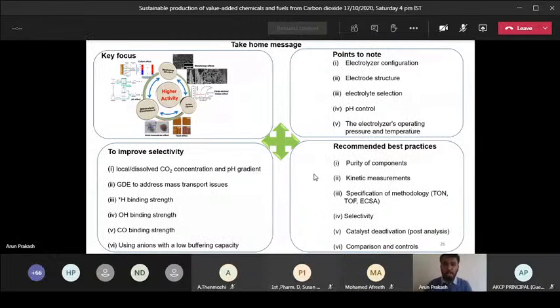And higher activity. When you want to get a higher activity, you have to focus on the electrolysis environment as the main thing, and the nanomaterial size, shape, grain boundary effect, phase effect, and also surface tailoring, oxide derived effects, morphology effects. Instead of having a nanoparticle, you can prepare a nanowire or a dendrite-like structure. More porous structures are more efficient for CO2 reduction because of the efficient CO2 transport. And cation effect, anion effect, pH effect, local pH effect, and grain boundary effect. These are all the effects you have to consider for best practice and to get the best results.